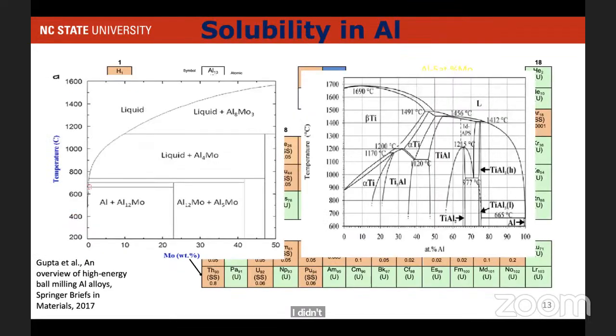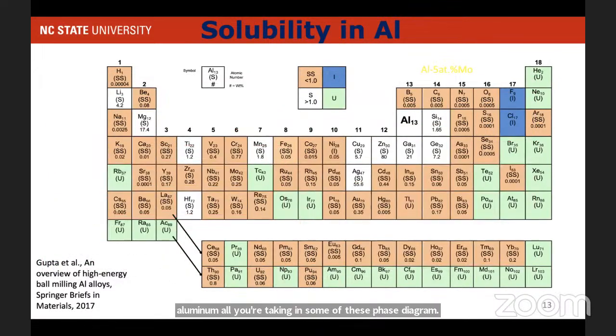But the problem here is, looking at the phase diagram, say aluminum moly or titanium, the biggest problem is the solubility of these elements, right? So we took the whole periodic table and put the maximum solubility of different elements. It's a color coded map. Let's take one example, chromium here. The maximum solubility of chromium is like 0.77 weight percent. Vanadium is 0.4 weight percent, and these are the maximum solubilities. If I go to room temperature, this drops down to like 10 power minus 7 atomic percent.